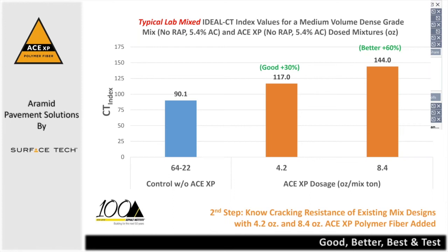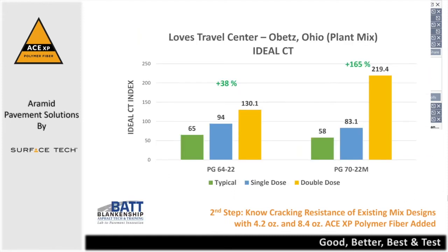So a 6422, 5.4% AC, no RAP in this mix, and this was pretty much a medium volume road, about a million ESALs, maybe a little bit more than that, is where this mix design is used in Kentucky. Came back with a pretty good number. Again, this is a lab mix, so 90.1, but we were still able to improve that with a single dose by 30%. And as you can see, as we get to that second dose, we've actually improved it 60%. And so the second step is to truly know how your control mixes are performing with a single and a double dose of ACE XP polymer fiber.